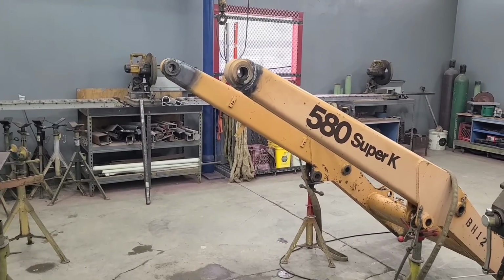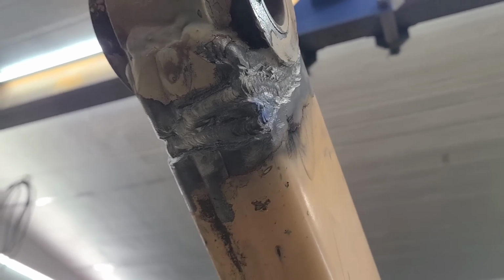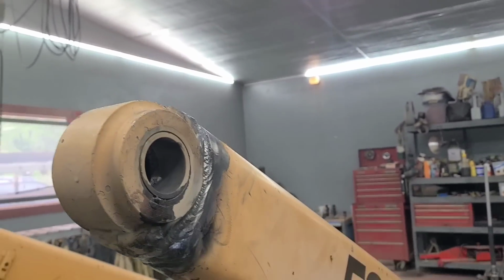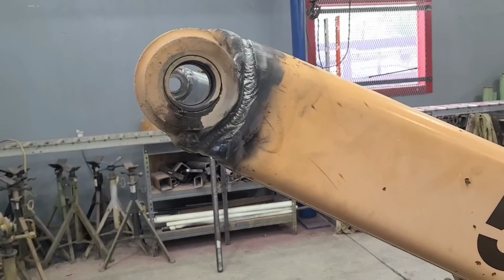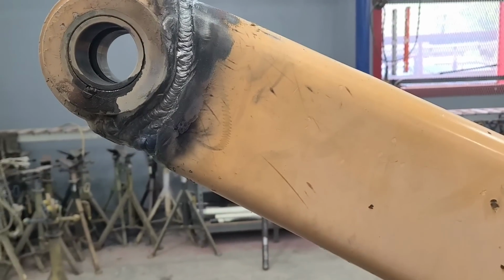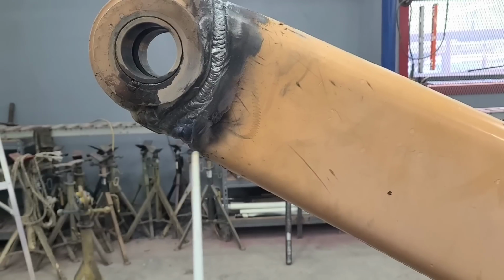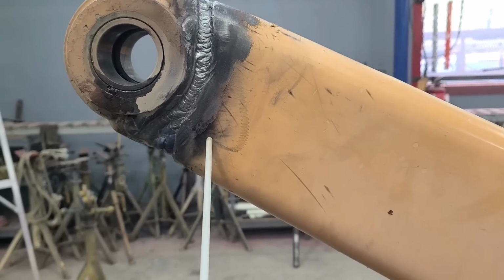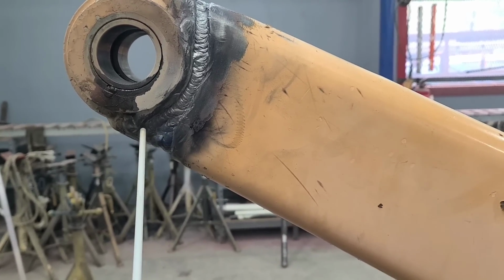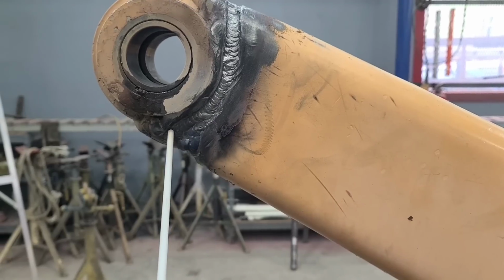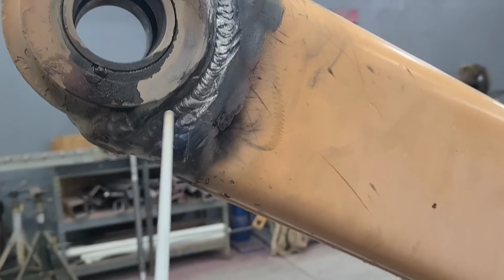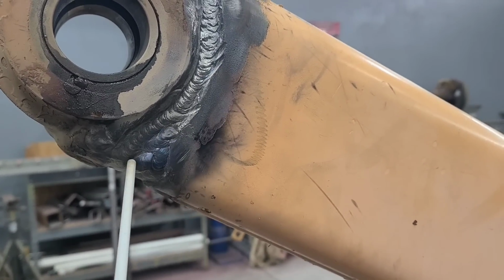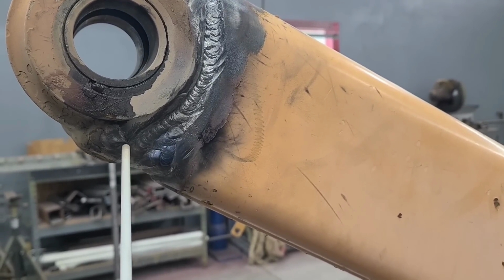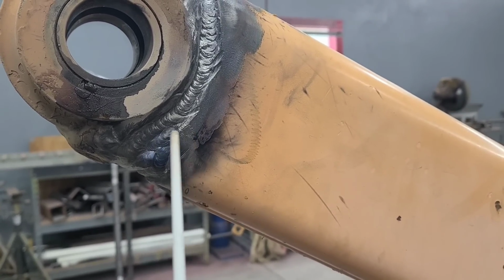Well, let's take a look at this first pass of 7018 we got in here. One pass of 7018 over top of the 2 passes of the pipe rod. Some of the things that I like to mention about running the 7018 uphill like this: when you manipulate your rod, see this part of this weld right here is kind of like you're moving up on a 45-degree angle almost, making this weld. But when you do that, you still need to carry that weld level.